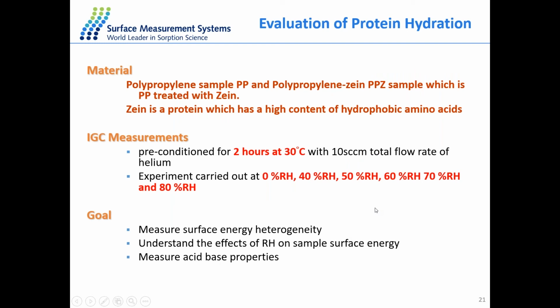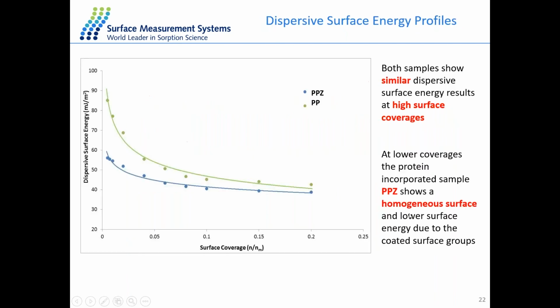The next example is relating to polypropylene material and polypropylene treated with a zein protein. So the purpose of the iGC-SEA was to understand the differences between introducing this zein protein, which has high content of hydrophobic amino acids, and we want to understand the protein hydration as well. So we want to introduce humidity on the surface of the sample. So we've introduced humidity at 0, 40, 50, 60, 70, and 80% RH. So this is the dispersive surface energy against some different surface coverages.